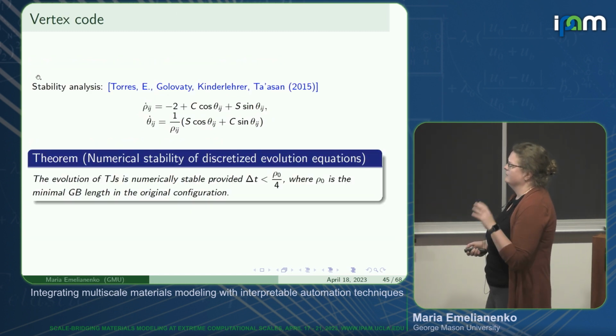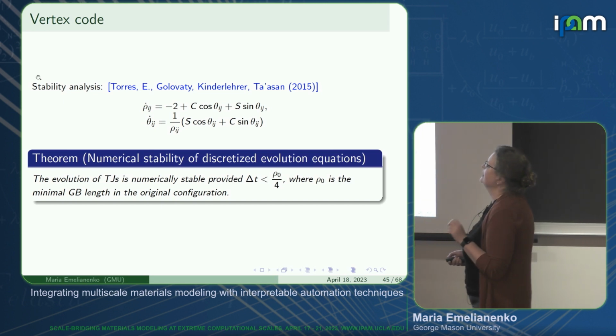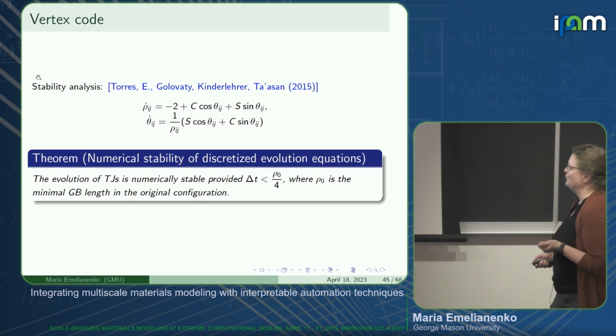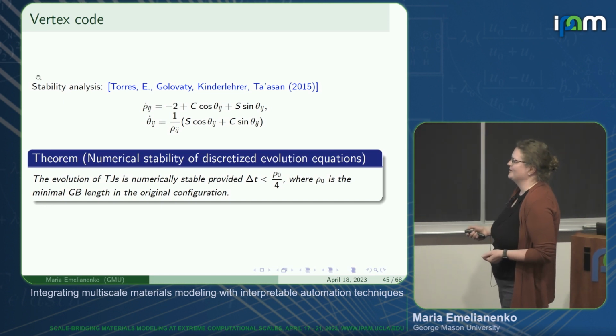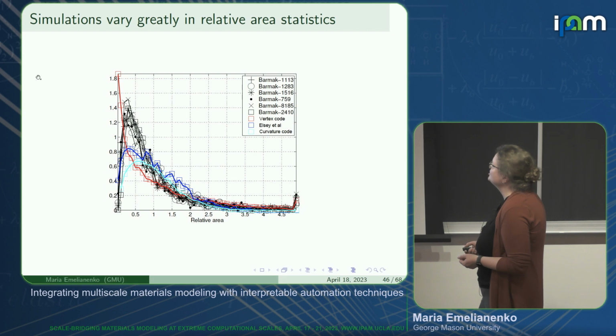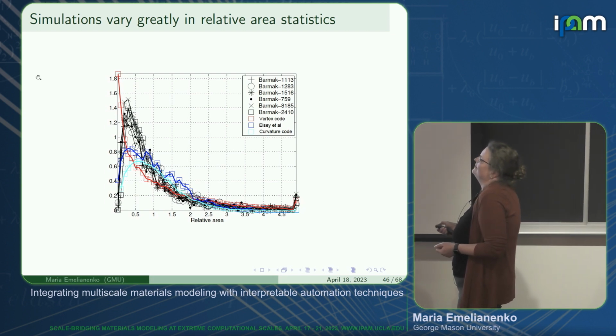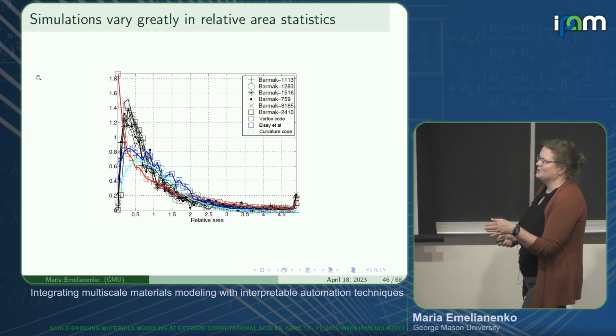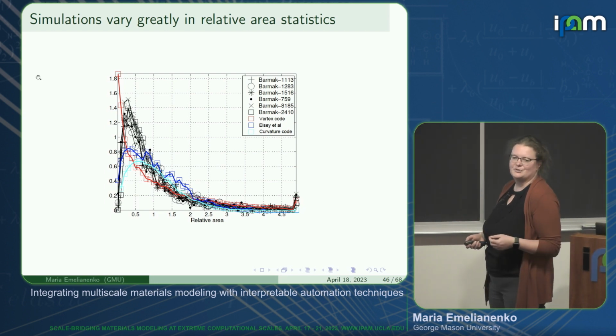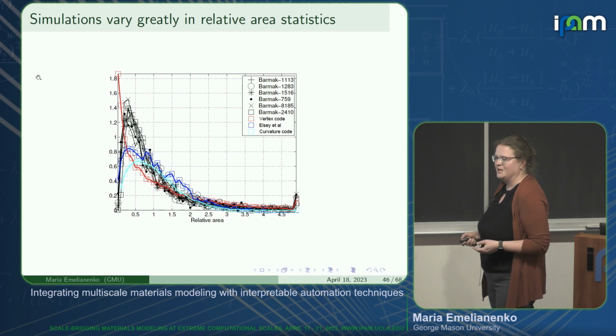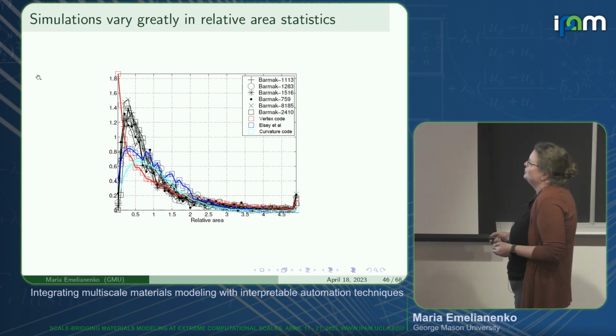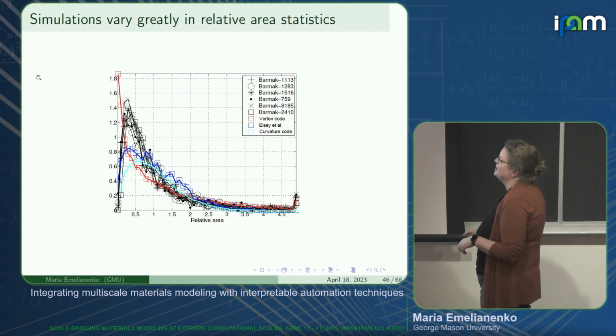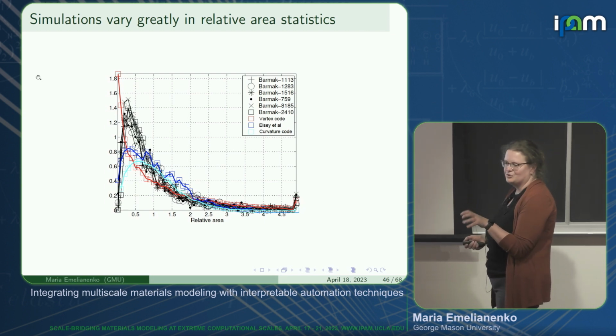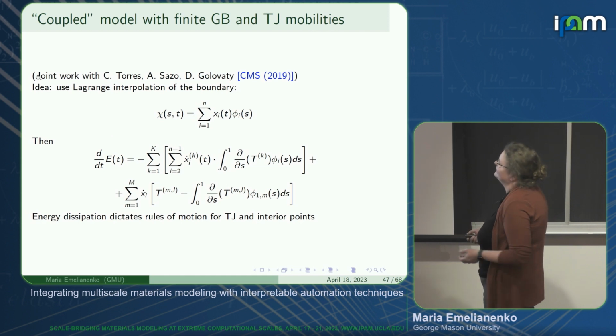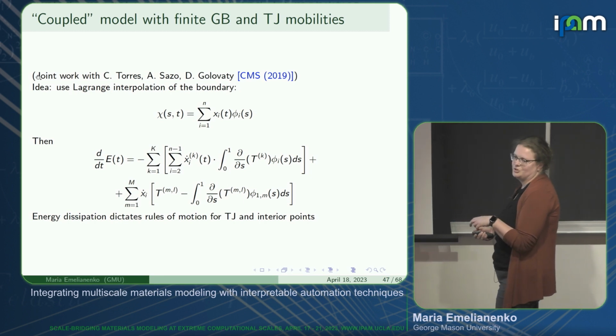So we actually have done a lot of work to prove that this particular implementation of the vertex code is stable. So we have stability analysis, kind of like a CFL condition type of result. And still, if you look at what happens to the results, they fall not exactly on top of the experimental prediction. And what we saw is that you can change where this curve is if you change these mobilities of the triple junctions. And so that motivated us to look into the development of this coupled model, which couples boundaries and triple junctions together.